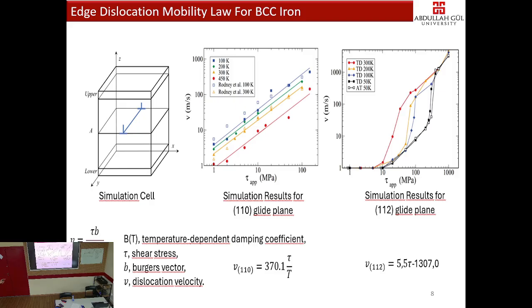Decrease, right? So increasing the temperature 100, 200, 300, but the velocity decreases. This is due to phonon interactions and phonon dispersion. So these are like maybe solid state physics, but it is not always. Once you increase the temperature, the dislocation velocity decreases. And the mobility law that is suggested for edge dislocation in the literature is v = τb/B.